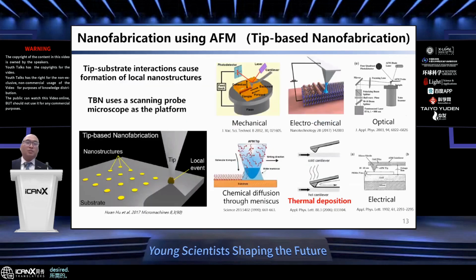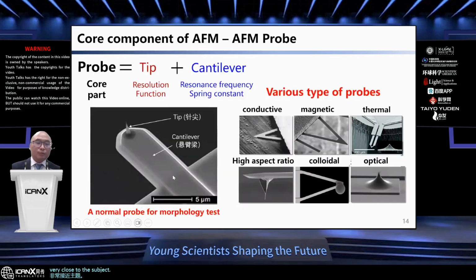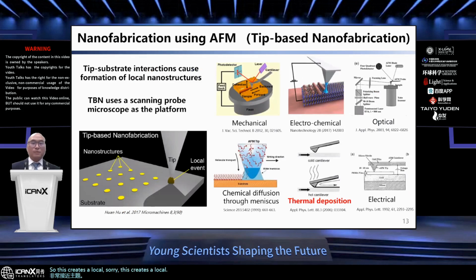Okay. So my PhD is focused on nanofabrication using AFM probes. You can imagine the AFM probe provides a unique scenario where you can have a tip very close to the substrate. So this creates a local environment. You can apply a mechanical approach, or if this is within a certain humidity, there will be a droplet, a meniscus, formed between the tip and the substrate. You can rely on diffusion to transfer molecules to the small region, or you can use thermal deposition. Basically, you heat up ink and do this. You can also apply electrochemical reactions, optical, electrical. So in short, tip-based nanofabrication uses a scanning probe to fabricate nanostructures.